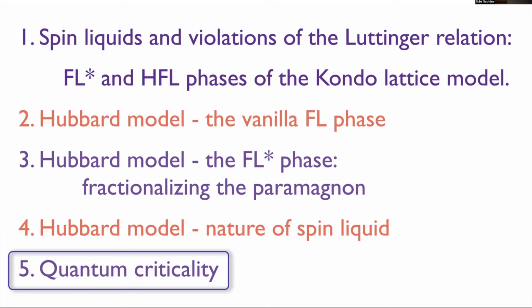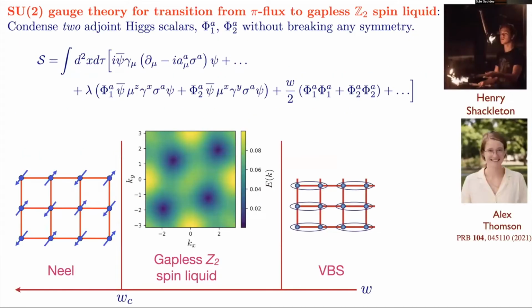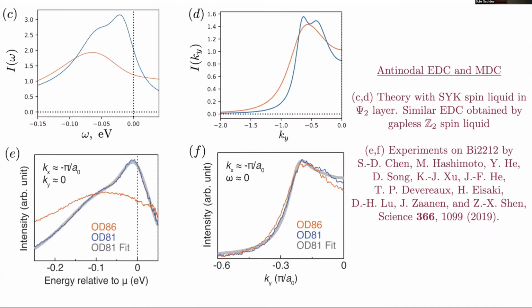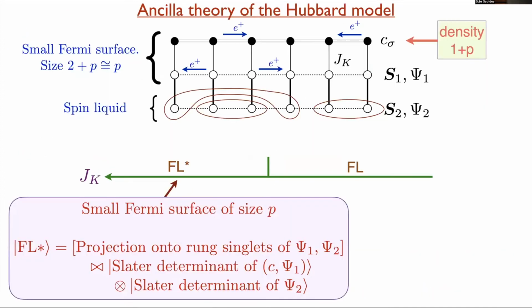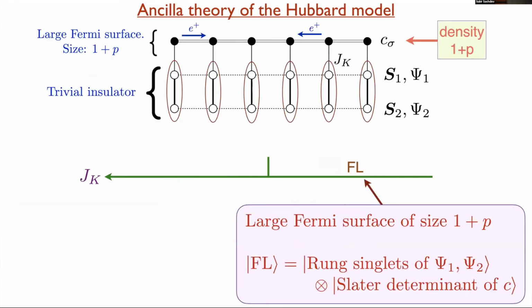So the spin liquid dispersion and the T1 hopping, the T1 can have many different choices. It works best if you take it to have the opposite sign. It's a hole-like dispersion, and you can also understand that because it's really describing a correlation hole of the electrons at the top layer. So the T1 has the opposite sign from the T. It could have second neighbor, third neighbor hopping. Yes, we do take that. So there are fitting parameters.